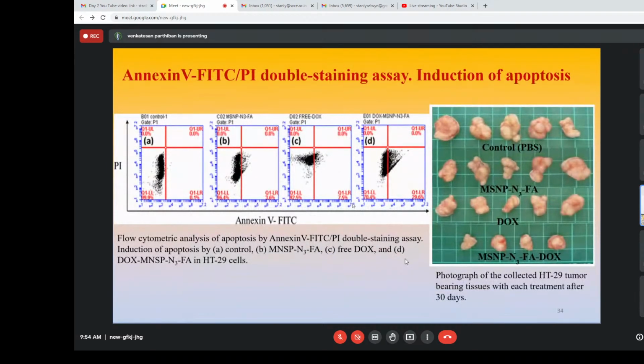Further, we check another piece of evidence with Annexin V and FITC-PI double staining, along with photographic images. We can see that in the control group and the doxorubicin nanoparticle group, the tumor size is suppressed compared with the free drug. And further we check the double staining. This one is only the control group, so we cannot see any apoptosis. But we can compare the free dox and the doxorubicin nanoparticle. These two images we can see here. This is only 7.5% for free dox, compared with the doxorubicin nanoparticle, where we see 29% apoptosis. So free dox gives only 7%, but the doxorubicin nanoparticle using the H2S-responsive strategy gives maybe around 30% apoptosis.